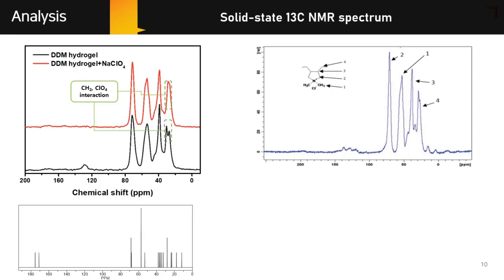This page shows the CNMR spectrum of DDM hydrogel, and main peaks appear before 50 ppm. Black line data is DDM hydrogel, and the red line data is DDM ClO4 hydrogel. The main peaks of DDM and DDM ClO4 were almost the same, and there was a slight change in the peak of the ClO4 anion bonding part. This graph shows that the chain structure of DDM has remained almost unchanged.